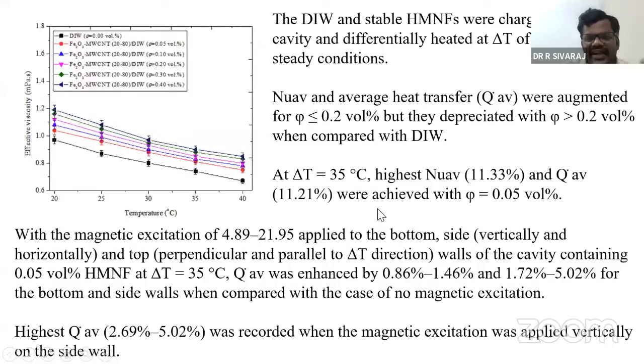So in this, importantly, we can observe that the average Nusselt number and the average heat transfer rate are being increased. For example, at 35 degrees Celsius, the average Nusselt number is increased up to 11.33% and the average heat transfer up to 11.21% when we consider 0.05% of nanoparticle suspension in the base fluid. And not only this, the impact of the magnetic field is being enhanced from 4.89 to 21.95 in the bottom side, that is, vertically as well as horizontally.